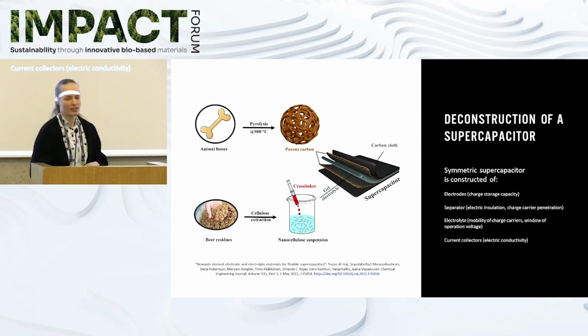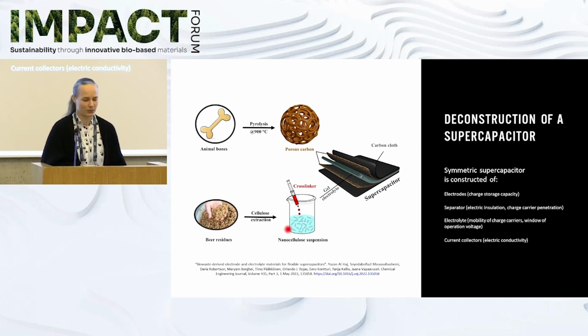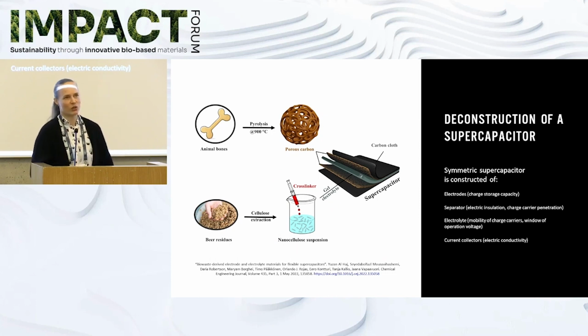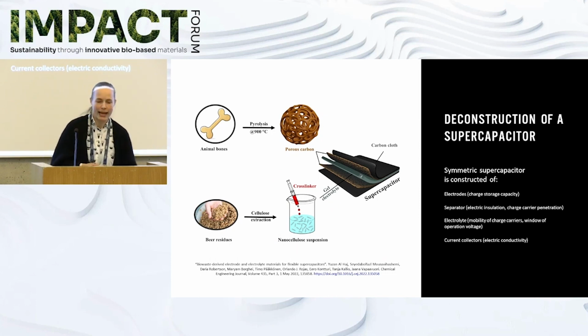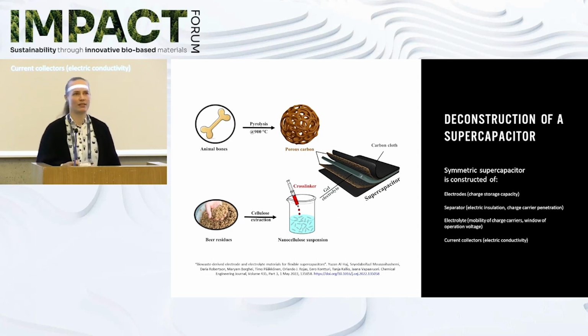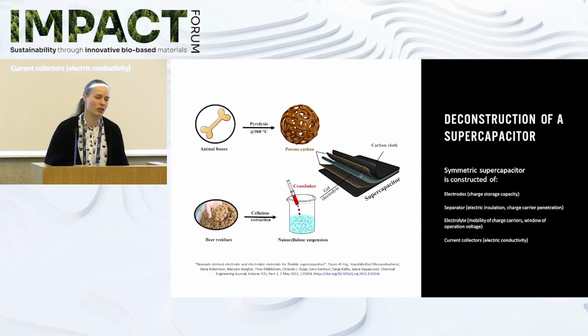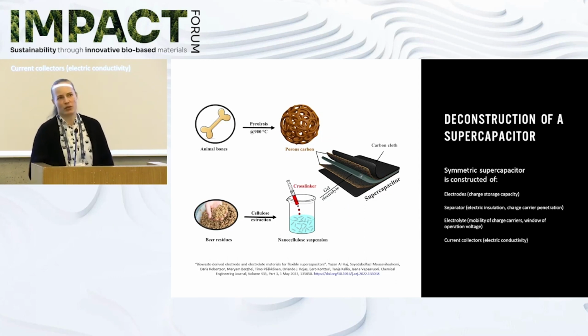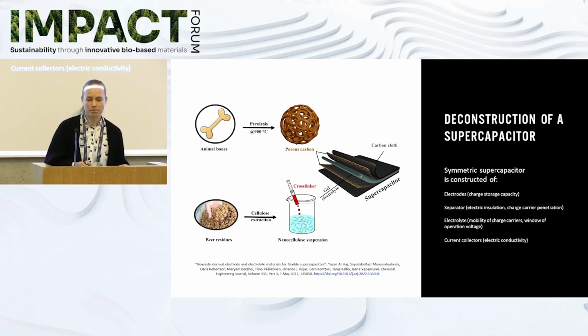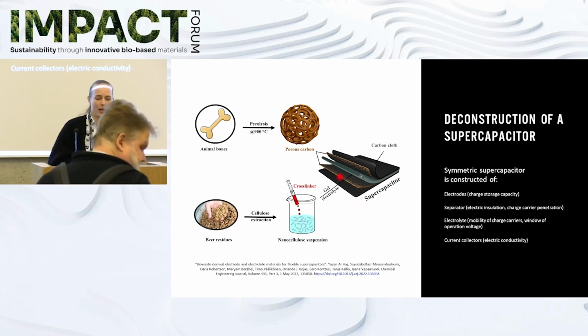So a few years back, this was work done when Finceres was starting. So we showcased with a bunch of nice people that pretty much all components in a supercapacitor can be derived not only from biomass, but pretty much from bio-waste. So for the electrode materials, we used animal bones, slaughter waste, so you can just pyrolyze it, you go to porous carbon, and that worked pretty nicely as an electrode. Then for the electrolyte, we applied brewery waste. We extracted cellulose nanocrystals out of the brewery waste, then ionically cross-linked it, and then made this sandwich.